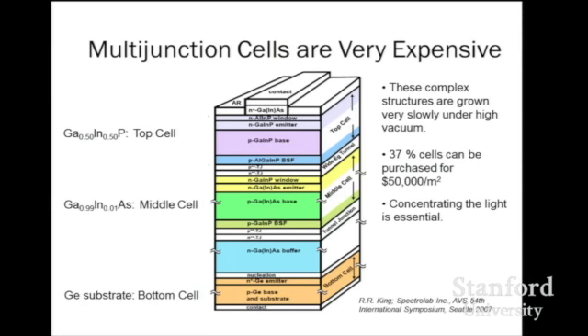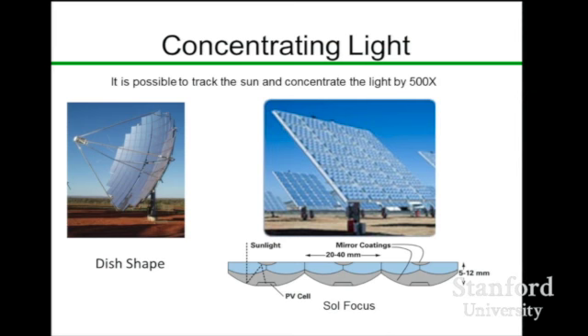But this is a very expensive technology. This is a cross-section of a typical multi-junction cell. There's around 20 layers in here. Every single one of those layers serves a critical purpose. And this is all grown slowly. There's a single crystal substrate, and there are low defects all the way up through this structure. So you can really only utilize these cells right now with a high level of concentration, and then that requires the tracking. And it's still not clear that the costs of the concentrators and the trackers will come down enough to hit those SunShot goals and be at 50 cents per watt.